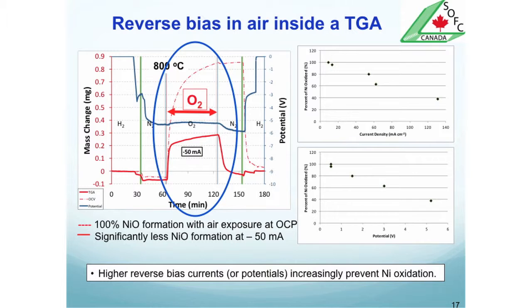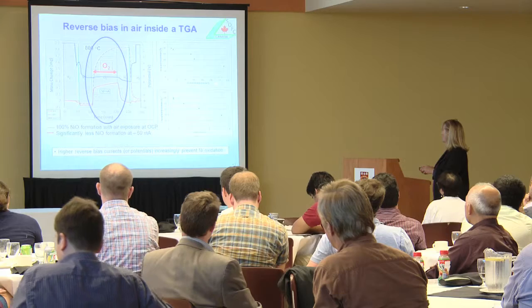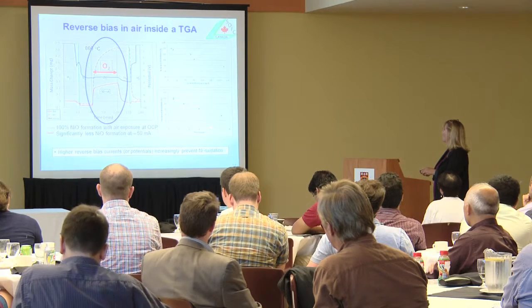This is percent nickel oxidized. This is 100 down to zero. Both of these are percent nickel oxidized. Remember, we don't want that. And this is with negative current density applied. This is with negative potential.